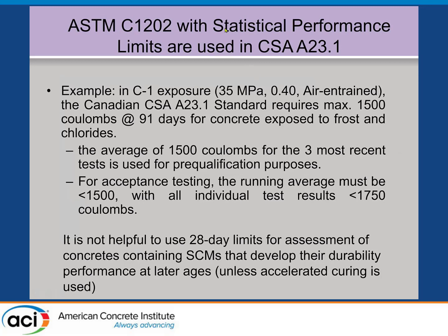But it was a real advance at the time. And a number of specs used 1202. The Canadian concrete specification adopted C1202 limits in 2004. And currently, for example, in C-1 exposure, which is our standard sort of the equivalent of a C2 exposure at ACI, so 35 MPa, which is about 5,000 PSI, 0.40 max water air entrained, we require 1,500 coulombs. We've set the limit at 91 days because if you set it at 28 days, the only way you're going to get there is with silica fume. If you set it at 91 days, then things like slag and some fly ash mixes can also make that limit.